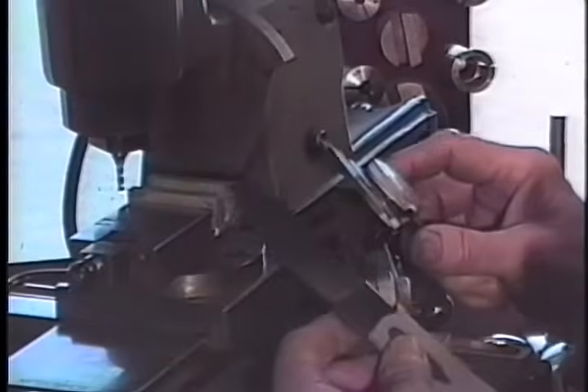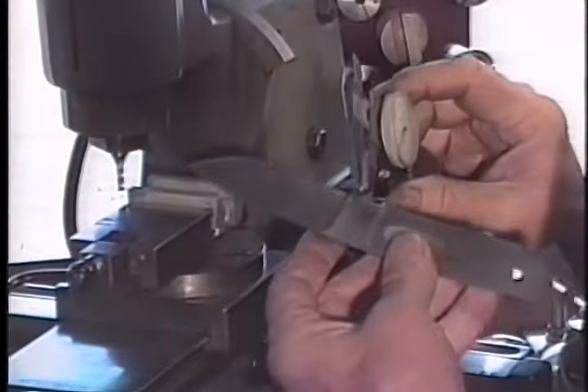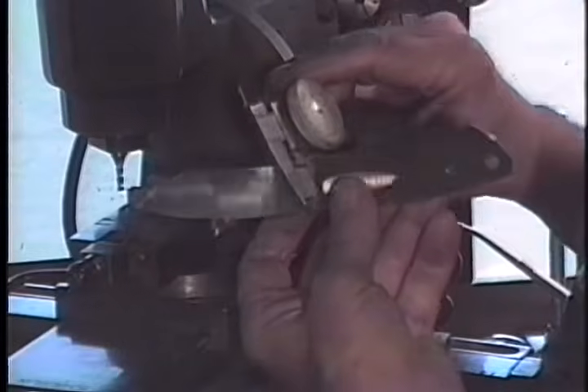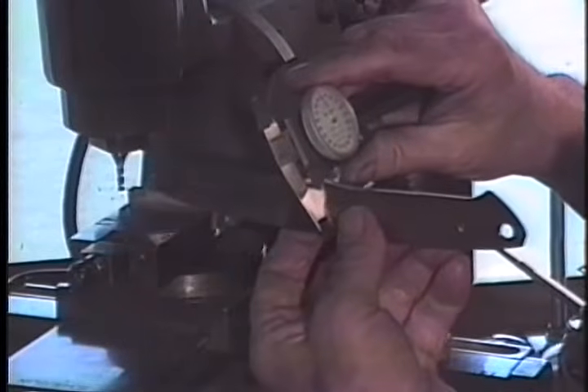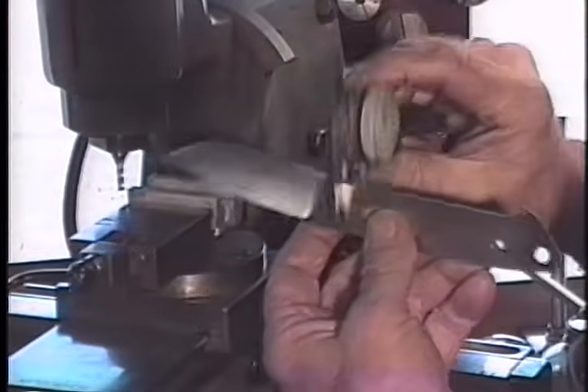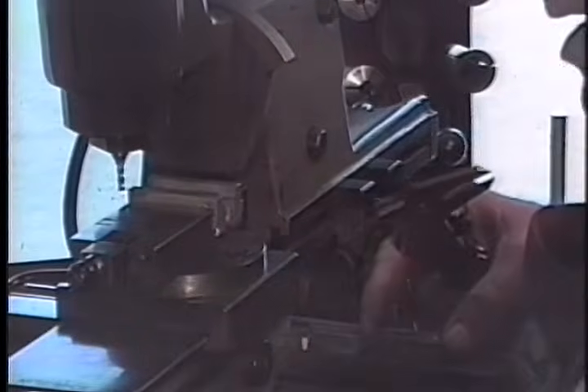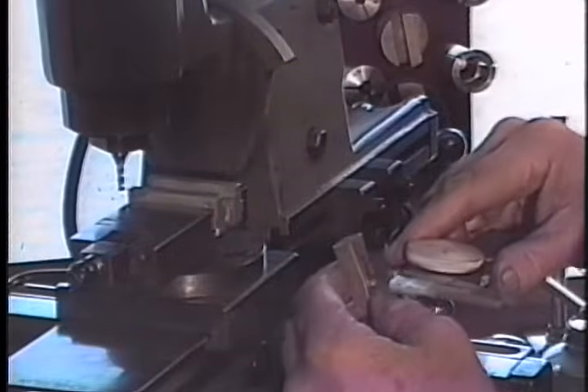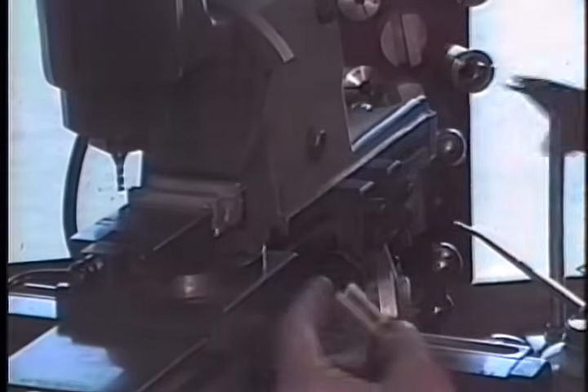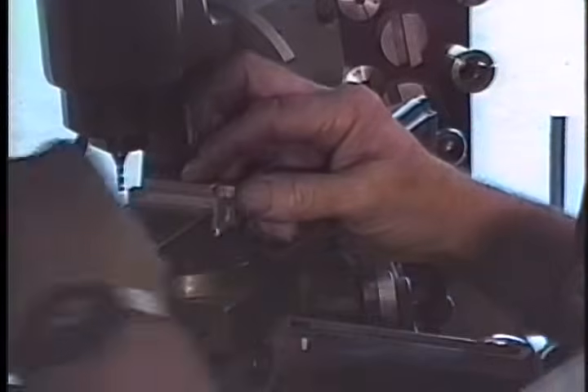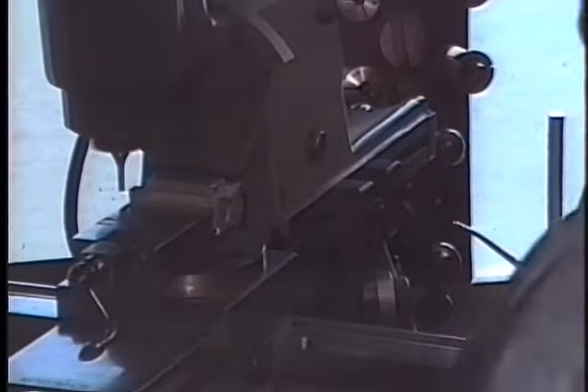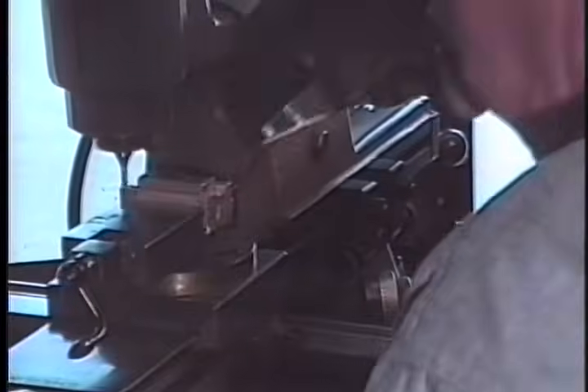What we're going to do now is fit the guard to the ground blade, and we do that prior to heat treat. Now this actually measures 0.196 thickness across the ricasso, and this guard's been pre-cut but undercut, and it's only about 192. So we're going to go into the milling machine, the little 6/8 mill, clamp it in place, and pick up this dimension we want.